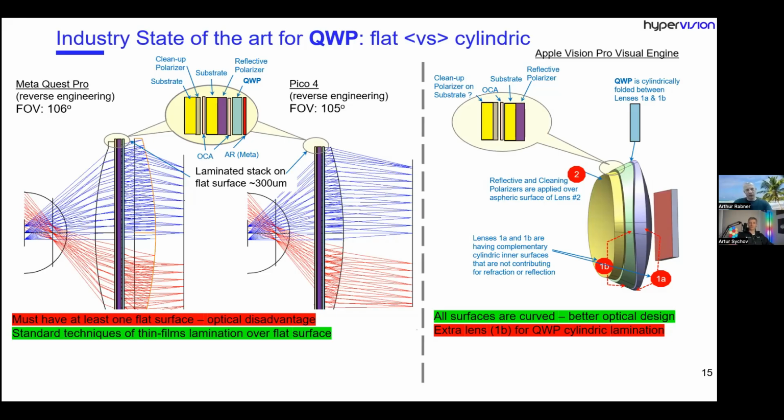But by the way, in Somnium VR1, each visual engine has two lenses in a stack, right? Yes. The question to you: are you making anti-reflective coatings on the lenses? Yes. Now, there are two types of anti-reflective coatings. The one used in prescription glasses reduces reflection from 4% to about 1%. And the second type is the dielectric one that can reduce it to 0.2 to 0.1%. The question: what type of coatings are you doing in your lenses?